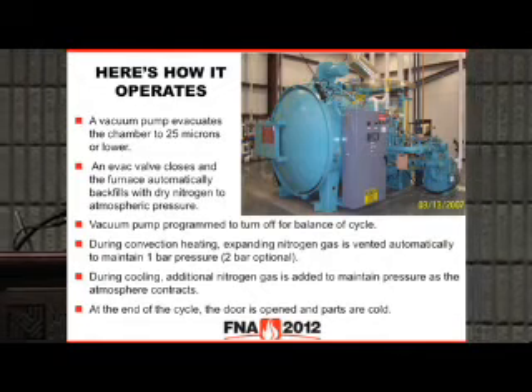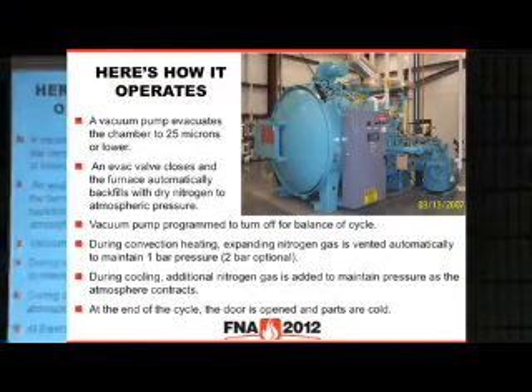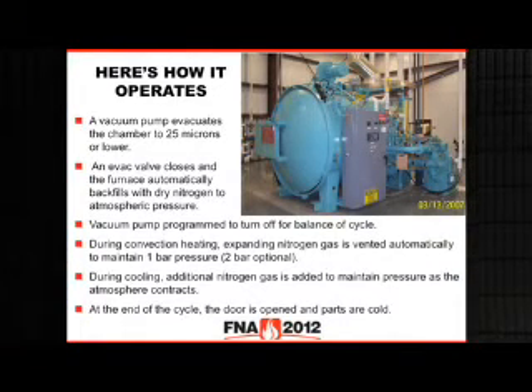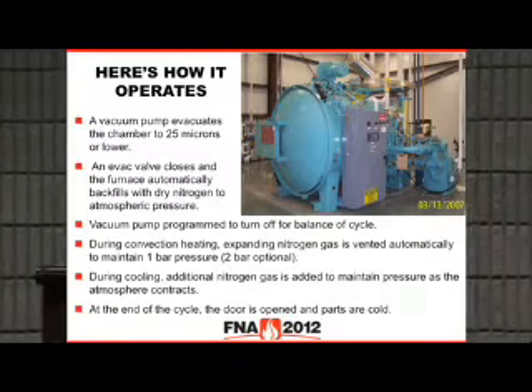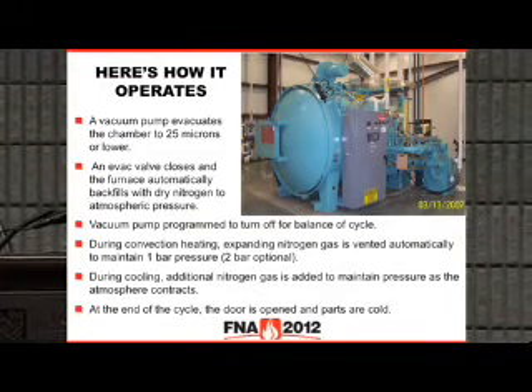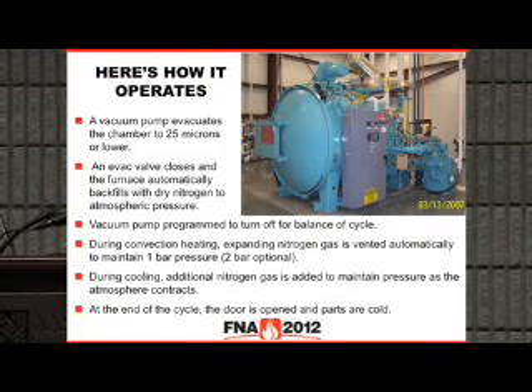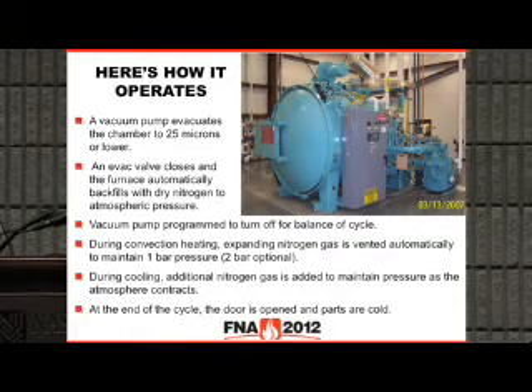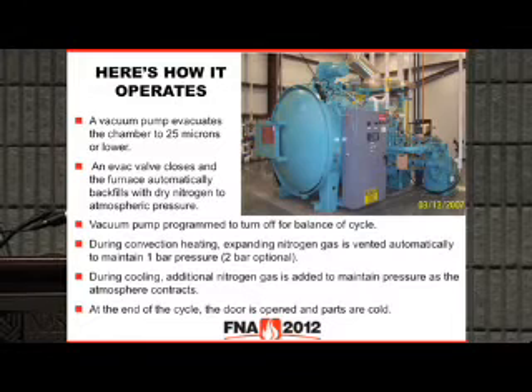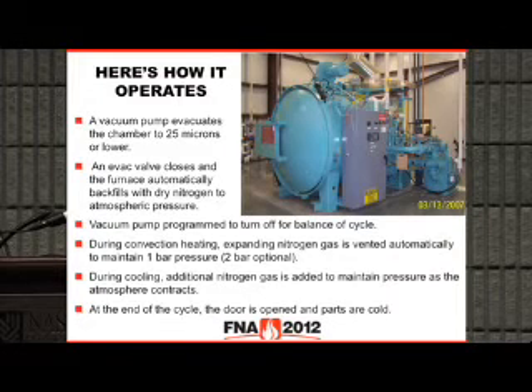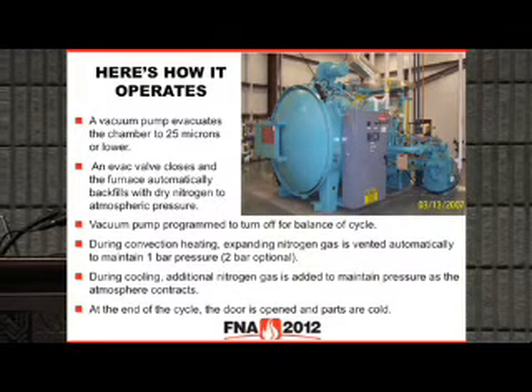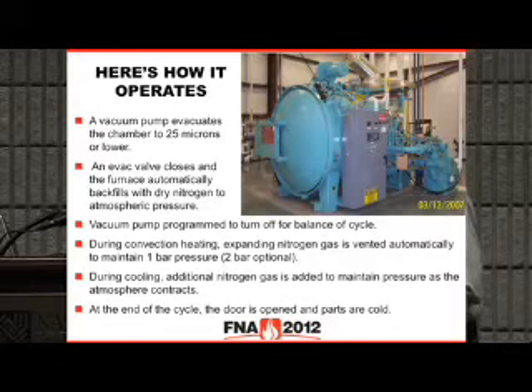A little bit about how they operate. They start cold. So when you approach the furnace, it's already down to room temperature from the last heat treat cycle. You're going to load the furnace, and then the vacuum pump turns on along with the evac valve opening. You'll pump down to traditionally 25 microns. You can go lower, you could go as low as 5 or 10. Some people say 50 or 100 microns is good enough. So that's up to you. It's just a setting on the control system.